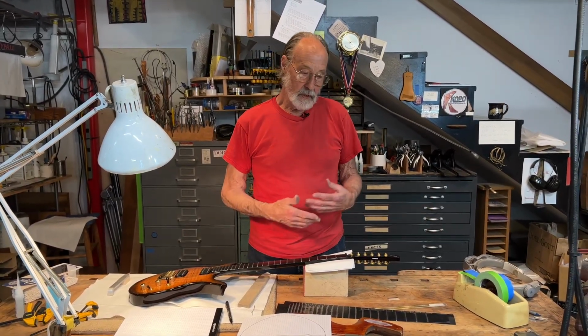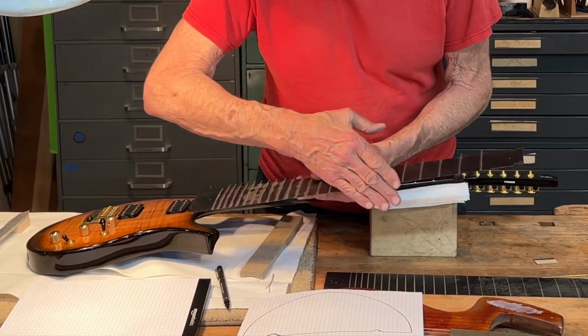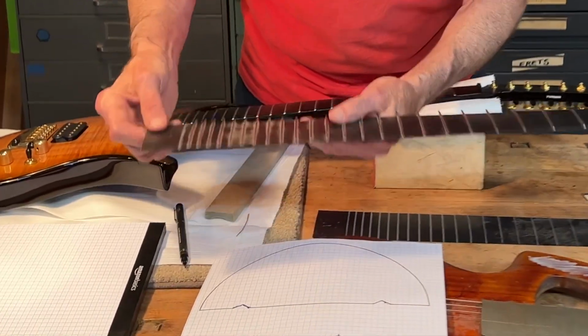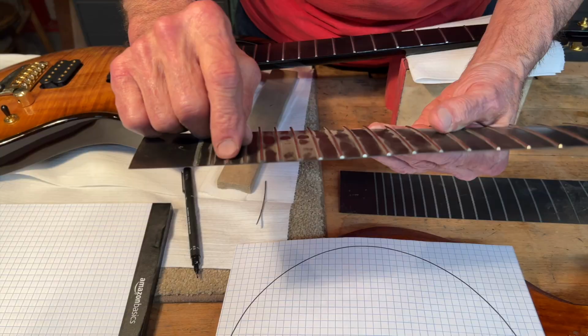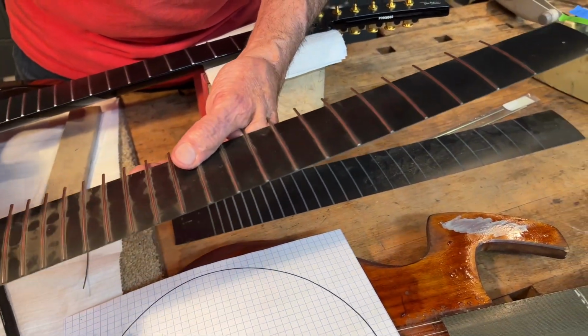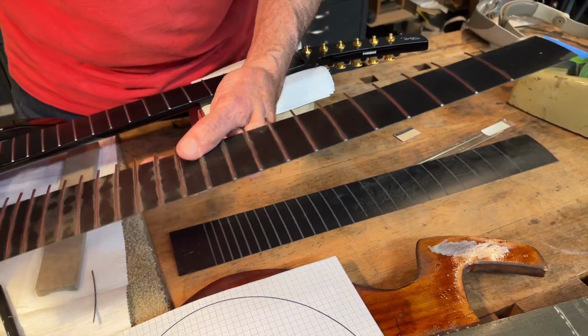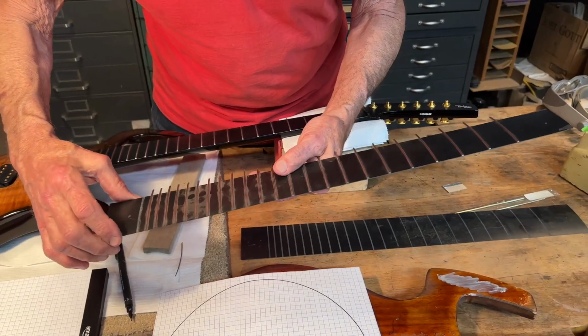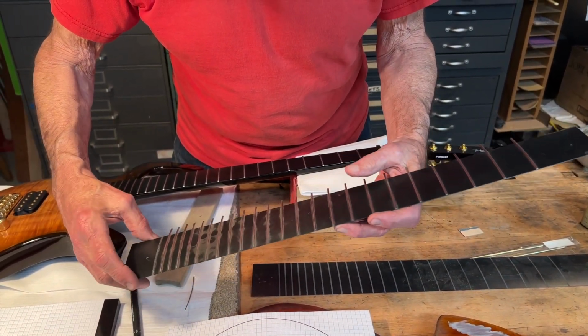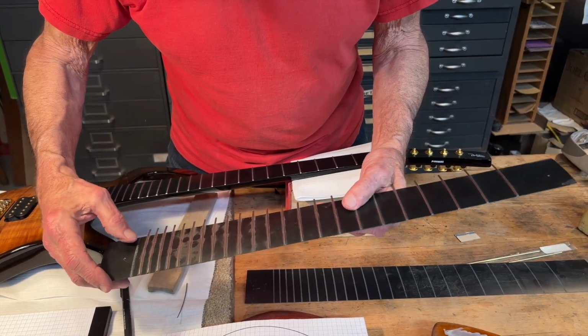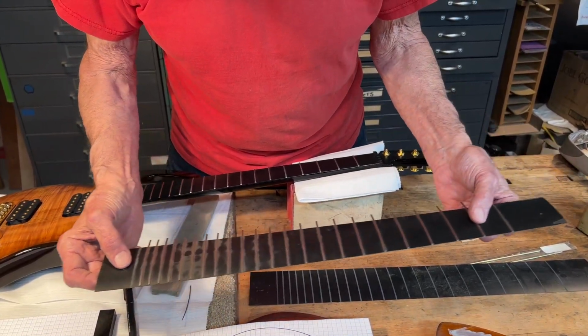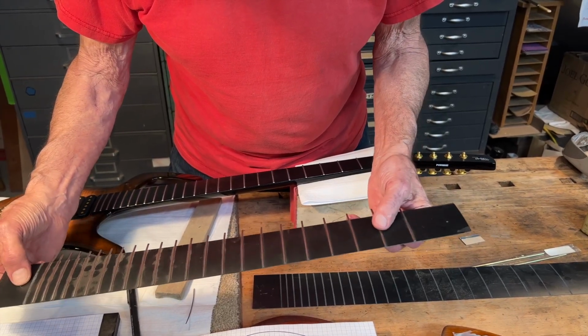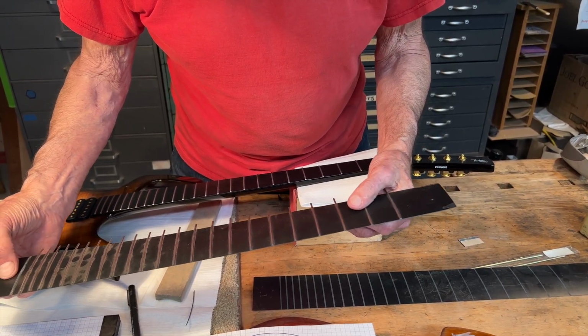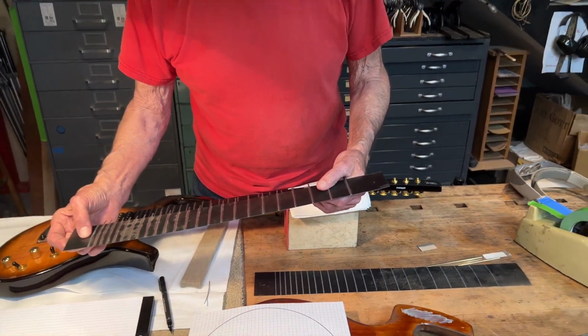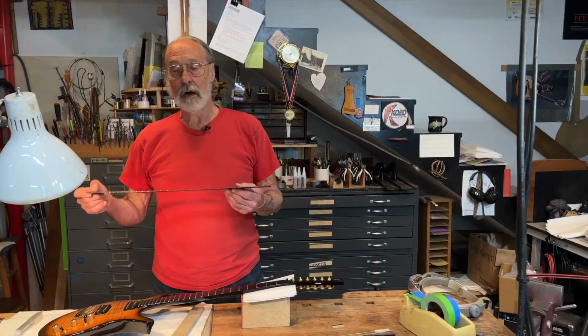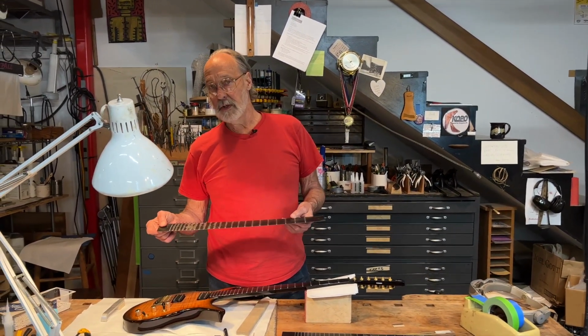We put everything together. We used a saw to cut the frets and the fretboard off. And you can see on this part, the saw has been used on one side, and it does a nice 22-degree bevel on the fret ends. Everything came out great. And the saw was a 2-inch diameter solid carbide saw, about 0.5 millimeter, 25 thousandths thick, with a lot of teeth on it. We fed the part very slowly with a hydraulic cylinder, a lot of control, very heavy clamping. And it worked great unless the bond was weak, in which case the fret would pop off. So our production method was also a quality assurance method.